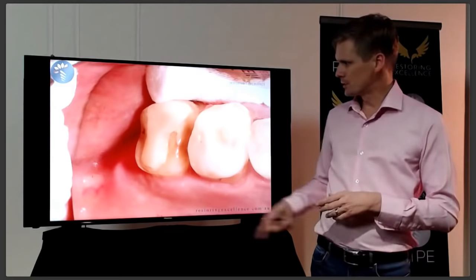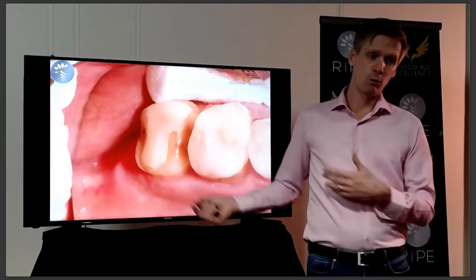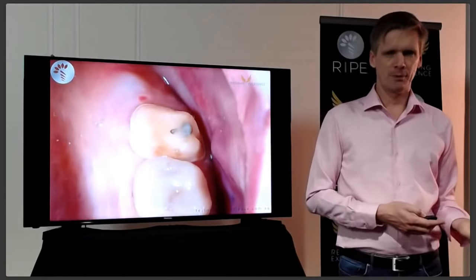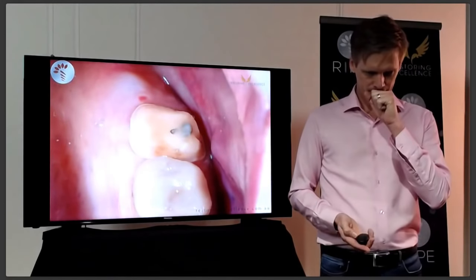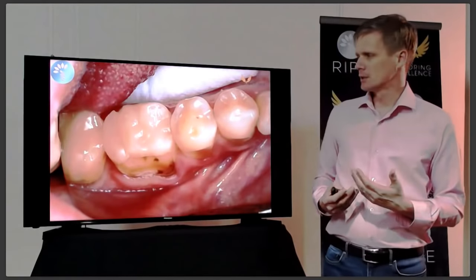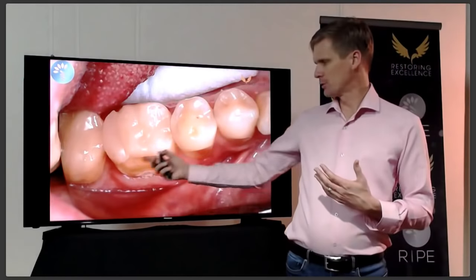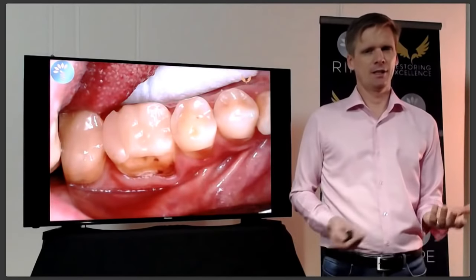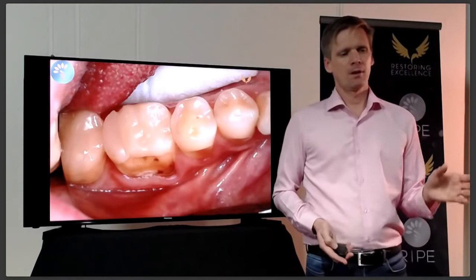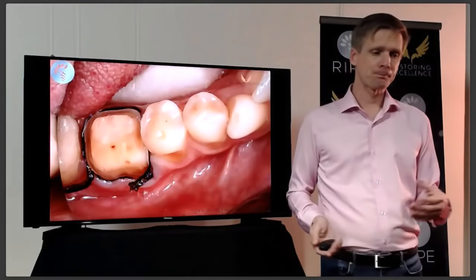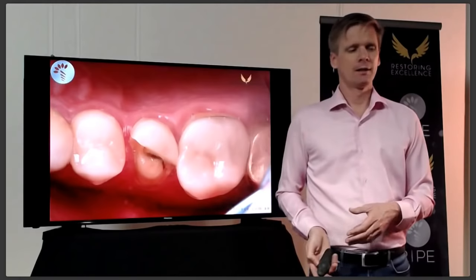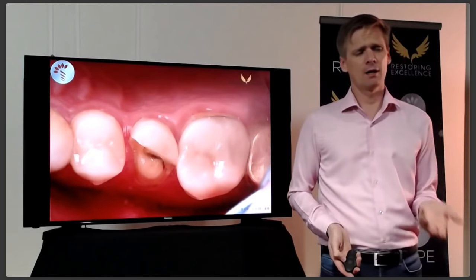It was too thin, okay? There's definitely thinness issues. It has worn and it broke. So I moved that one to a gold prep and we did a gold crown there. Now, we did have some issues on the lower. You can see that it was all bonded to dentine down here because there was a class 5 lesion and then the feldspathic. So this is more at about 8 years. Once again, it became a gold crown. And then another feldspathic porcelain crown fractured on a premolar. It became a full contour zirconia crown.